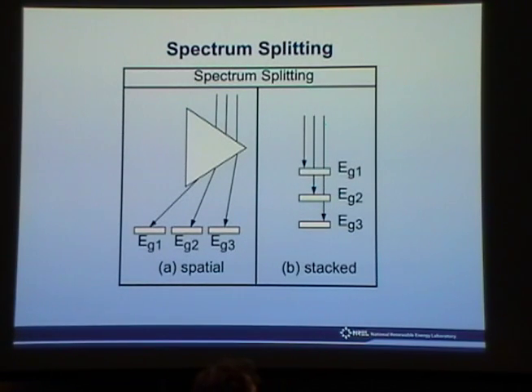The more common way of doing it is to stack the cells one on top of the other, either by growing them separately and then stacking them, or by growing them all together, one on top of each other. You start with the highest band gap on top, it absorbs the highest energy light, everything else is transmitted through, and you put the next band gap below that, that absorbs its region of the spectrum, everything below that is transmitted through, and so on.